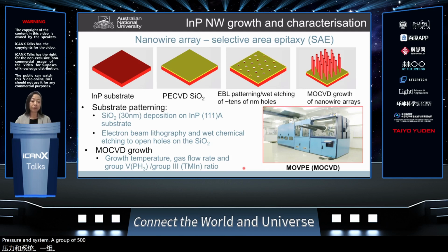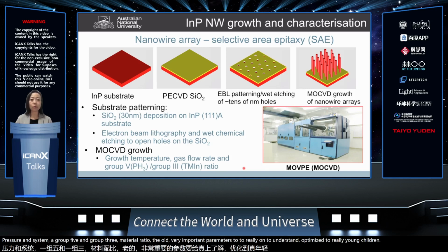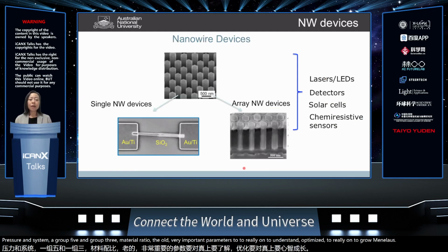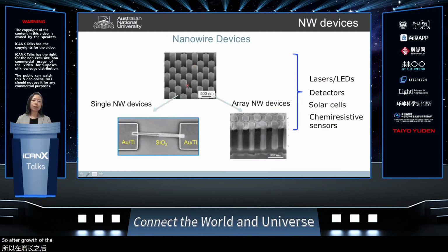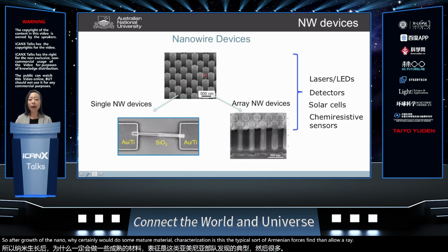The group V to group III material ratio, they're all very important parameters to understand and optimize in order to grow nanowires. So after growth of the nanowires, certainly we do some material characterization. So this is a typical indium phosphide nanowire array grown in our lab.